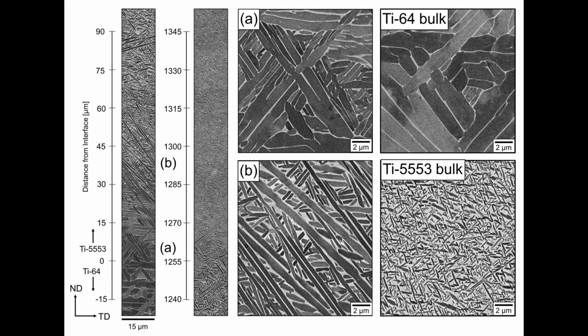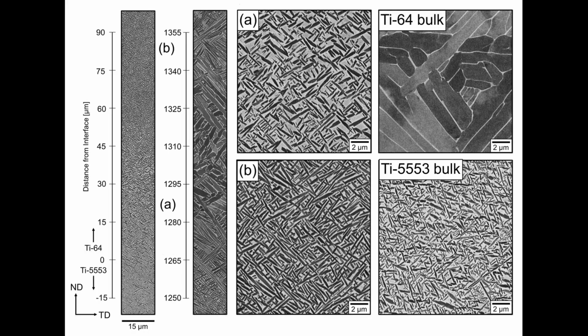As deposition continues, the microstructure changes in a stepwise fashion for the next 2 to 3 layers until the nominal Ti-5553 composition is reached, as shown in these backscatter electron micrographs. In contrast, when transitioning from Ti-5553 to Ti-6-4, a very different microstructure gradient is found.